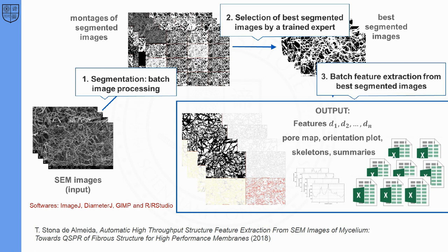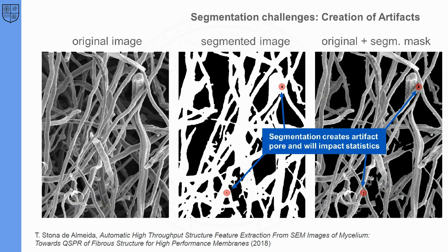The process of image segmentation and feature extraction is automated initially, when several filters designed for artificial fibers are applied to all images, creating 15 segmented images for each original SEM micrograph. A trained researcher must then visually inspect the segmented images and decide on the best segmentation. If adequate segmentation is found, DiameterJ extracts several features from the image. We should note that the mycelium network is a three-dimensional mesh that ideally should be characterized with a tomography-type method. Scanning electron micrographs are inherently two-dimensional, limiting this study. Estimating depth in an SEM micrograph is also challenging, since depth is not related to light intensity in the image.